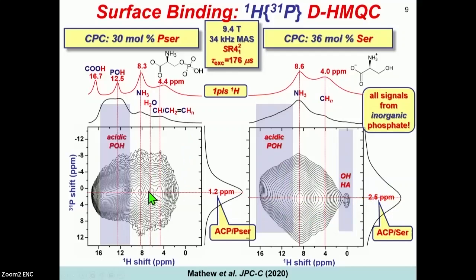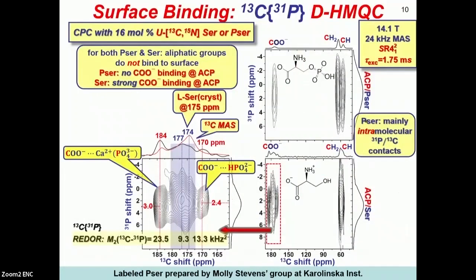Then the corresponding spectrum from the phosphoserine-doped cement is very similar in the proton region associated with the organic protons. In the high ppm region, we see correlations between acidic protons and both organic and inorganic phosphate groups. What we will take a look at next are the proximities between the carbon-13 sites and the inorganic phosphate groups. And here we obtained powders of uniformly carbon-13 and nitrogen-15 enriched serine and phosphoserine. And we prepared one cement each from those precursors, cements with 16 mole%.